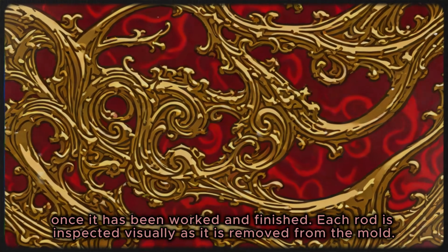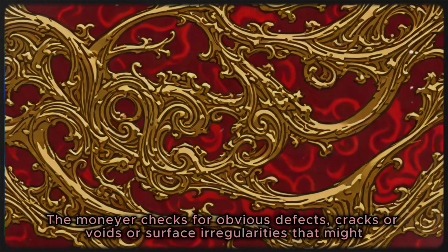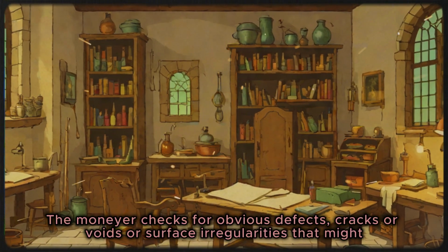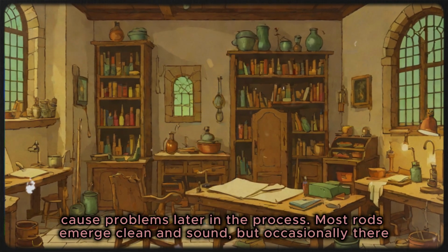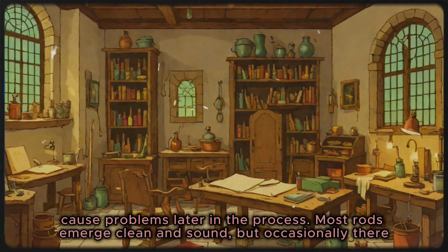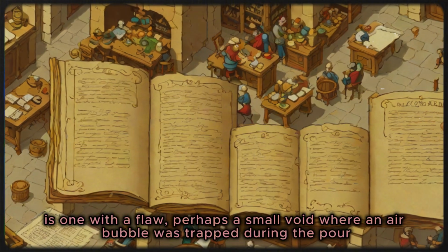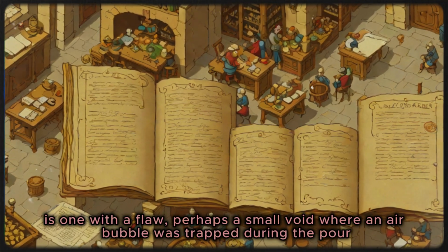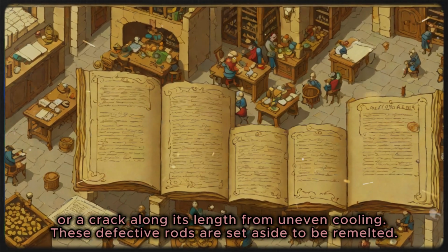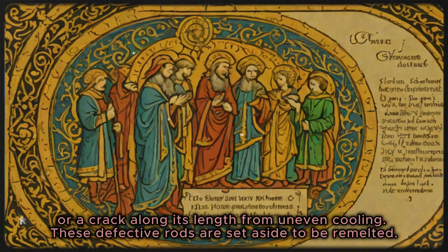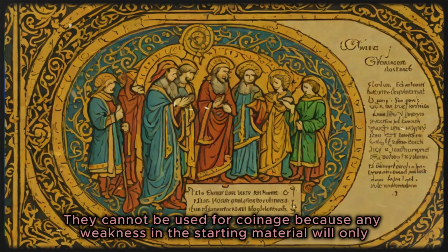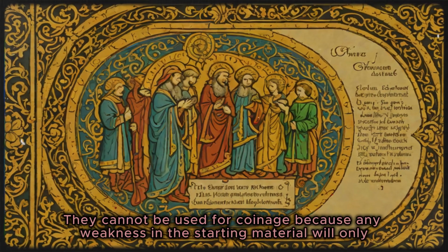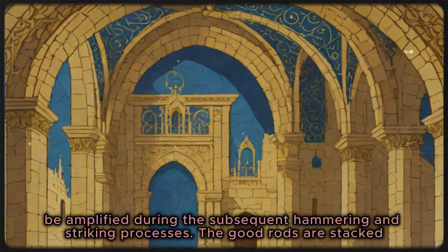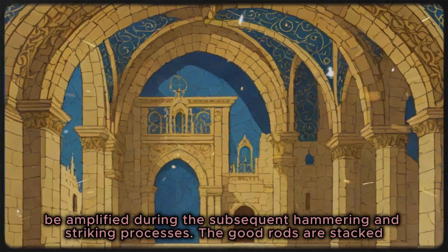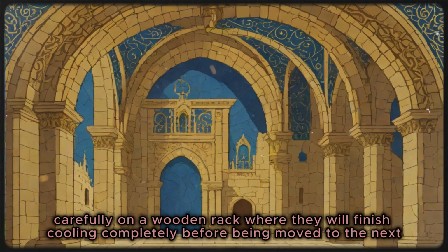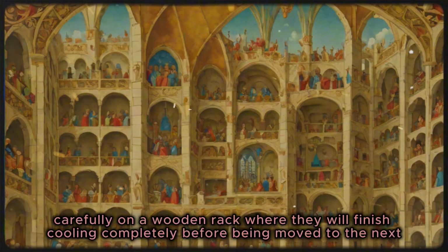Each rod is inspected visually as it is removed from the mold. The moneyer checks for obvious defects, cracks or voids, or surface irregularities that might cause problems later in the process. Most rods emerge clean and sound, but occasionally there is one with a flaw, perhaps a small void where an air bubble was trapped during the pour, or a crack along its length from uneven cooling. These defective rods are set aside to be remelted. They cannot be used for coinage, because any weakness in the starting material will only be amplified during the subsequent hammering and striking processes. The good rods are stacked carefully on a wooden rack where they will finish cooling completely before being moved to the next stage.